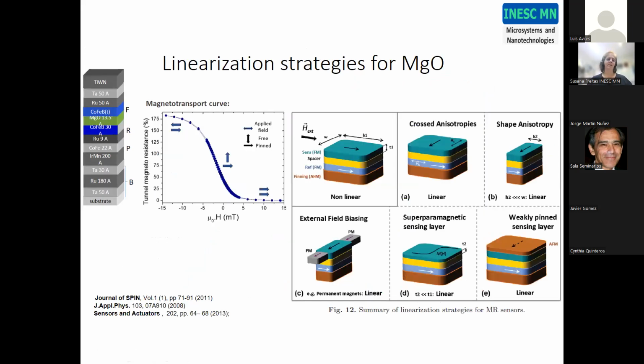And then the core difficulty here is how can we have a linear sensor? Because if you look at a magnetic material, a ferromagnetic material has a square loop, a square characteristic. So how can we get rid of the coercivity and the hysteresis? How can we have a linear transducer instead of a square transducer? All this requires strategies to control the angle between the free layer and the reference layer. I'm not going to go into detail for all of them. I will describe some of them in my next slides, but essentially there are several, and there is good knowledge on this topic. We actually have a review paper where we cover all these strategies that enable creating, under specific conditions, linear responses for essentially all magnetic stacks.